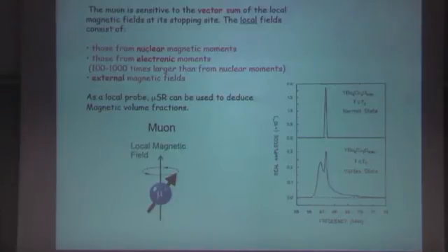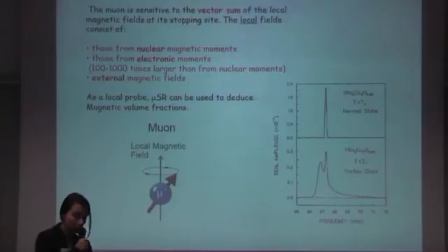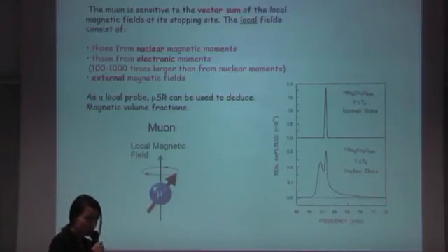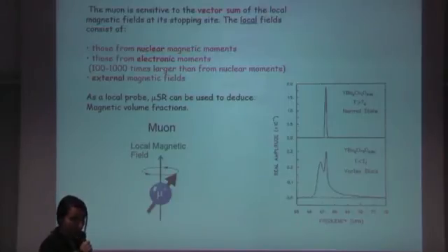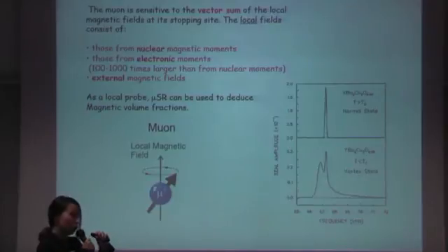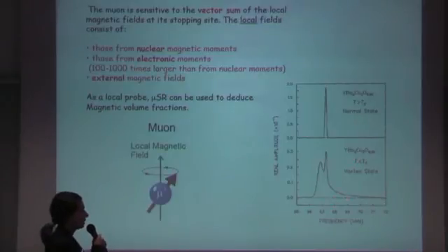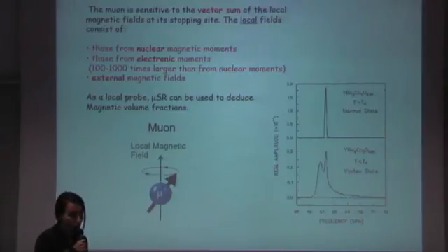Looking in the frequency domain is more intuitive. If you start with a superconductor in the normal state under an external magnetic field, you observe in the frequency domain a peak corresponding to the frequency of the external field. As you go to the superconducting state, this peak is still there but lower, because the external field only penetrates to within the penetration depth, and it spreads due to decay over the penetration depth. In the vortex state, or as flux starts penetrating, you begin seeing peaks appearing at different frequencies, and that carries information on what local magnetic fields are present.